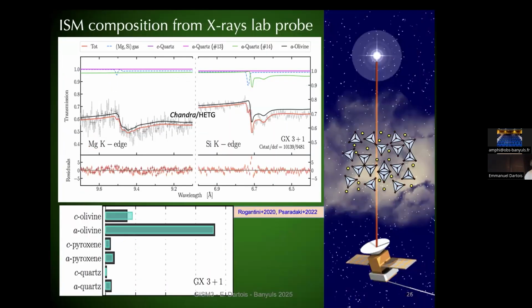This can be applied to observations by looking at X-ray sources. And to do so, you still need to perform all the experiments that I showed you just before. So by using standards of the different compositions you expect to have in space, and then by comparing here the magnesium K, the silicon K absorption along different lines of sight, you can try to make a spectral decomposition of the composition you get along this line of sight. Here, these spectra were much better fitted using amorphous olivine and a slight amount of crystalline olivine.